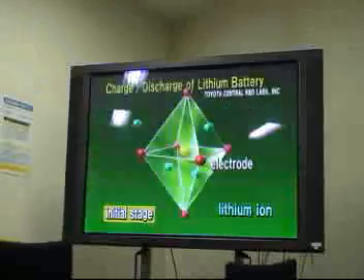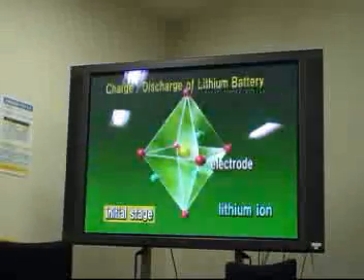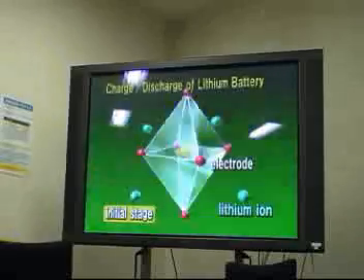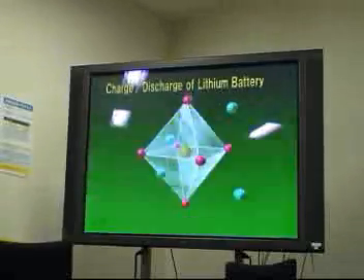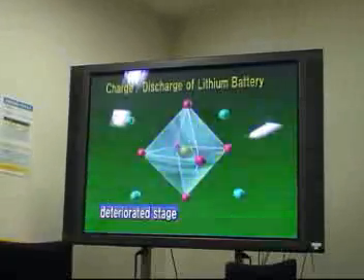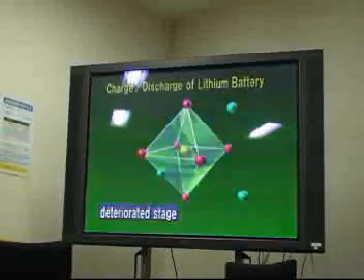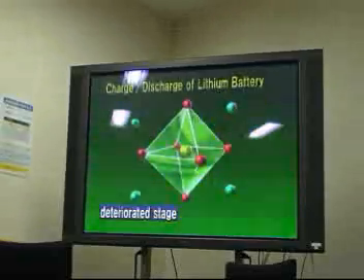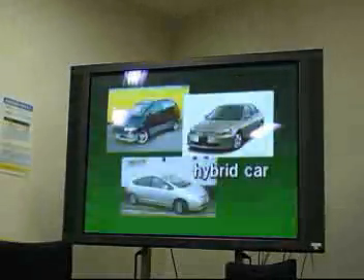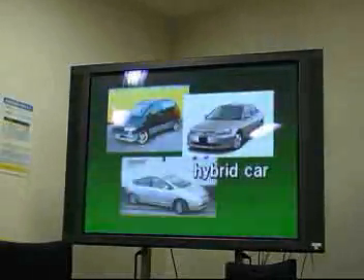Spring-8 has also helped to determine why battery capacity fades over time by observing the charge-discharge cycle on the atomic level. It was found that degradation is caused when the crystal structure, which initially consisted of deformed octahedrons, changed due to repeated charge-discharge cycles to become more regular. This finding has allowed the substantial extension of battery life, which has significantly contributed to the development of hybrid and electric cars. Synchrotron radiation is also useful in developing bumpers.